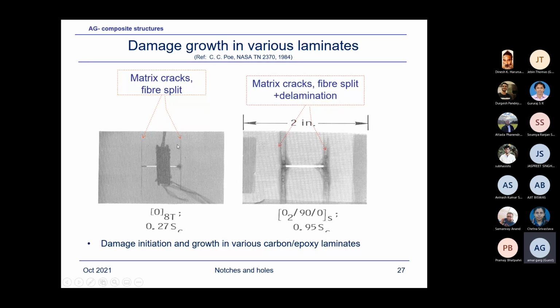So I also experienced in one of my studies the unidirectional laminate that it just split into 3 parts. This is separated, this is separated. So 1, 2, 3. Clean. 0 to 90S layup, also because there are a higher number of zeros, you find even though there's a 90 layer, still the crack is propagating along the load line. So why I wanted to show you the effect: we call in our study the self-similar crack growth and non-self-similar crack growth. If the crack propagates along this line, that is self-similar. Otherwise, non-self-similar. So the importance here is that in composites, you would rarely see a self-similar crack growth. They are non-self-similar.